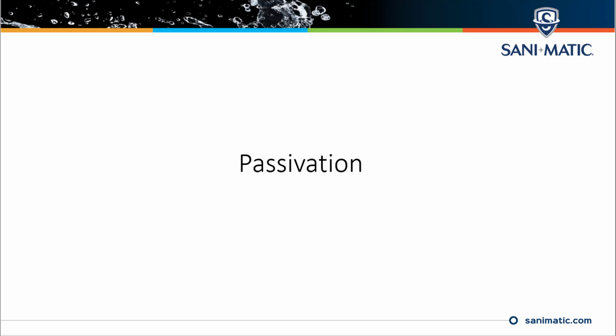So when people do a passivation, they're usually doing some sort of a citric. We used to use nitric acid. The whole reason for that is we're trying to strip away everything from that surface so that it can be exposed to oxygen for that period of time, but it isn't something that happens in an hour. You need to have residence time for that passive layer to form.